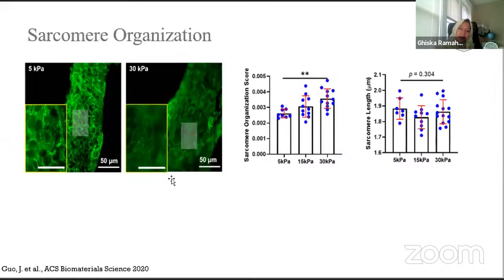Then we can also see here that in 30 kPa we have more uniform or more aligned structure of the sarcomere, while this one is pretty random in direction. But in 30 kPa, it's more uniaxially aligned, which is good because in our heart, all of the structure of the cardiomyocytes is very in line or highly aligned. So here we can see the sarcomere organization structure is quantitatively more aligned, but it doesn't give any effects to the sarcomere length.